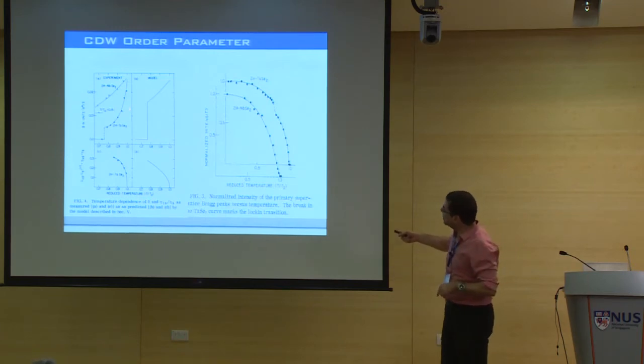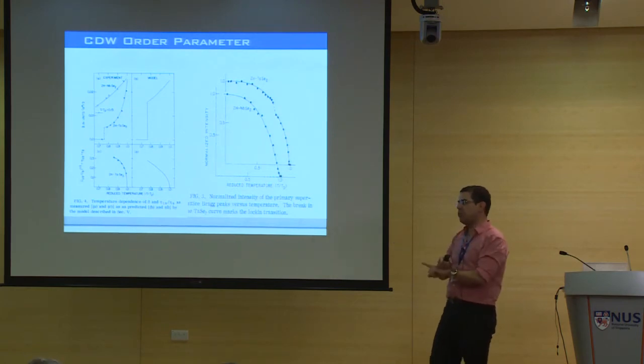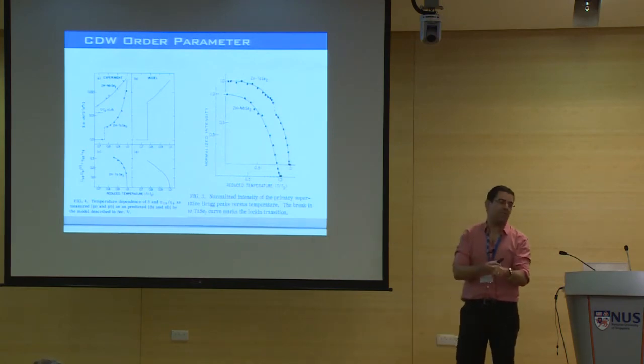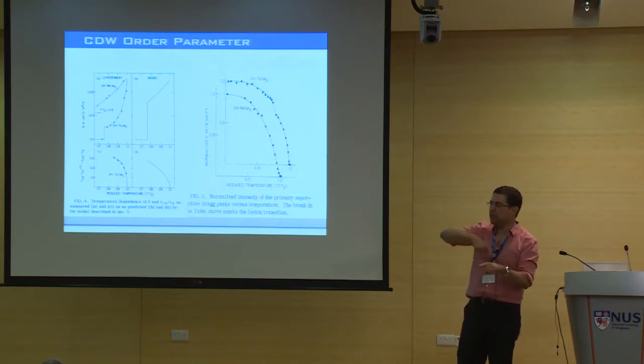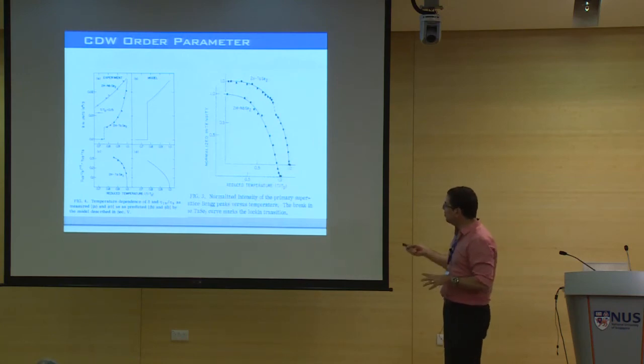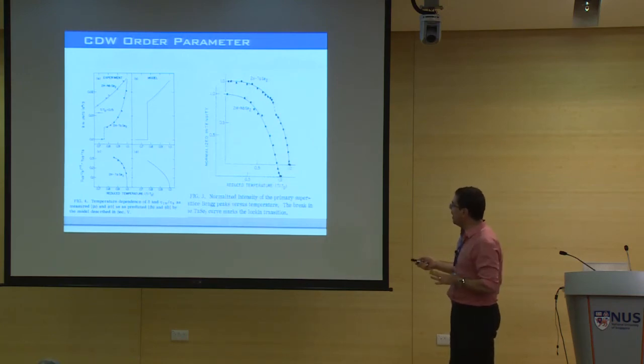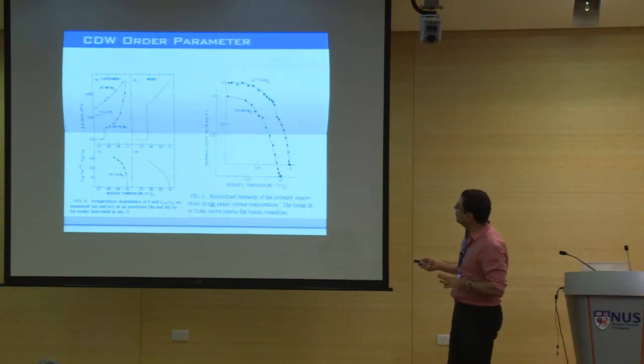But then, for instance, you look here at tantalum diselenide, there is a lock-in transition at low temperatures, and now the wave vectors actually set with the same phase. Okay? There is what's called a phason mode in these materials, which has to do with the freedom that you have to change the phase around. Okay? So it's all very well measured in neutron scattering.